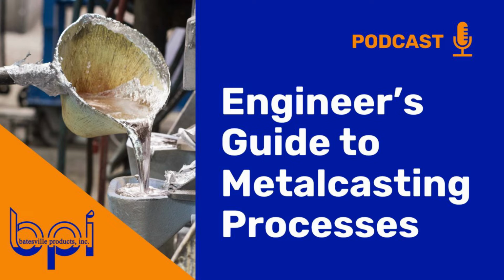In permanent mold casting for sure, because it's less prone to failure than sand casting or die casting. The reason behind that is, in sand casting, you have a lot of porosity potential or shrinkage potential, or even shifting in the tolerances just because you're building out of a sand mold. So you have to repeat that pattern.